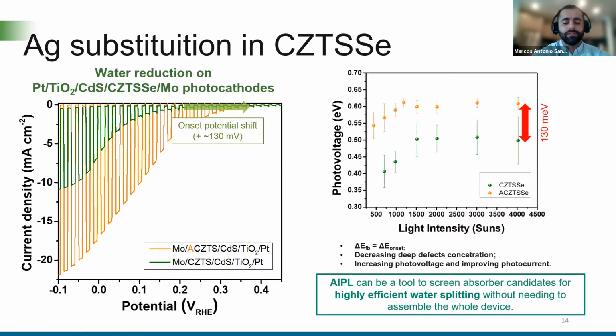So by plotting the photovoltage calculated from the PL curves versus the light intensity, we found the conclusions are the same as was obtained before for the copper zinc tin sulfide selenide photocathodes. We mitigated the concentration of defects. The flat band for the silver substituted CZTS is more positive, suggesting the annihilation of the detrimental defects.